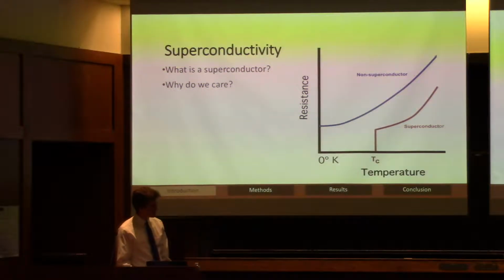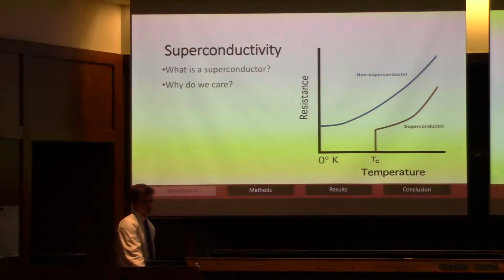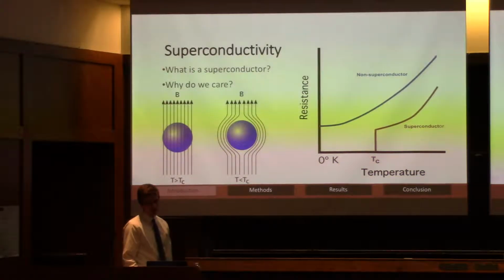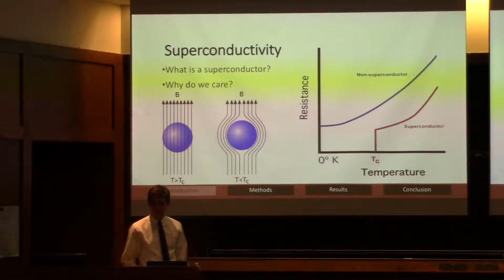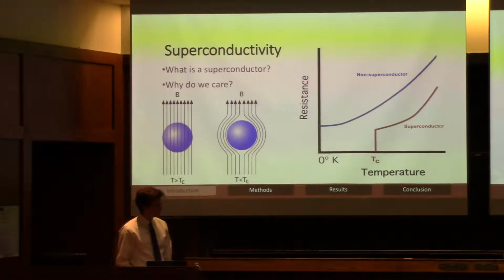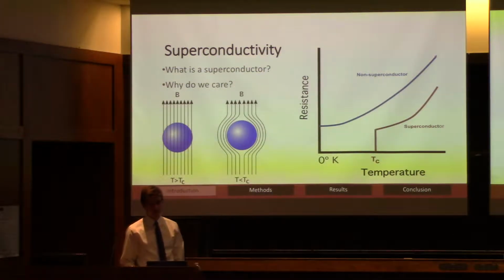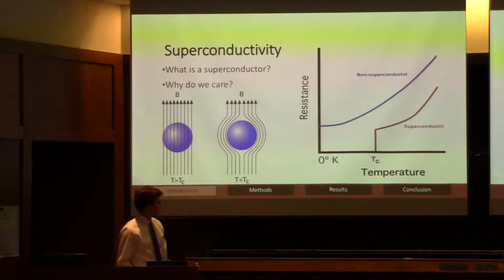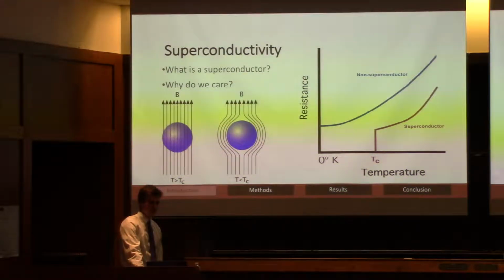The second macroscopic property of a superconductor is what's called the Meissner effect. And this means that when you put a superconductor in an external magnetic field, the superconductor will expel that field. And it does this by inducing currents in the superconductor to cancel that field out. So that's what this is a picture of. When you cool that sample down below its critical temperature and it starts superconducting, it expels external magnetic fields.